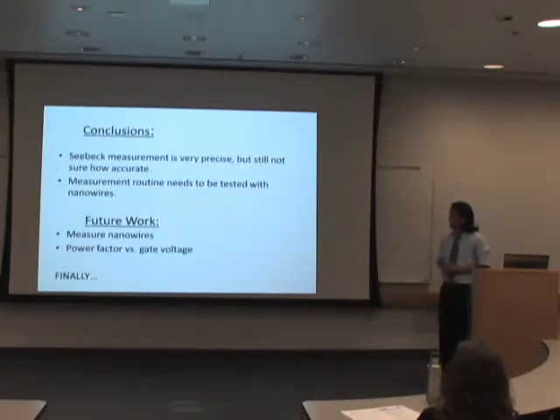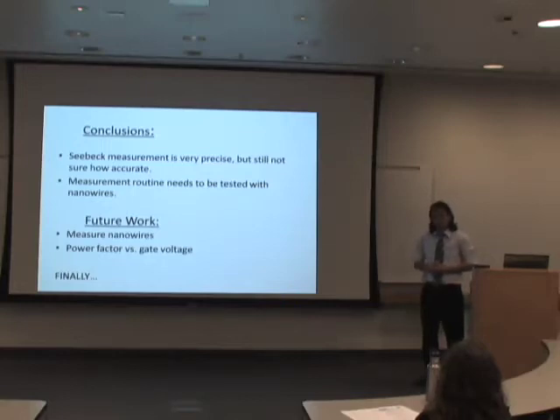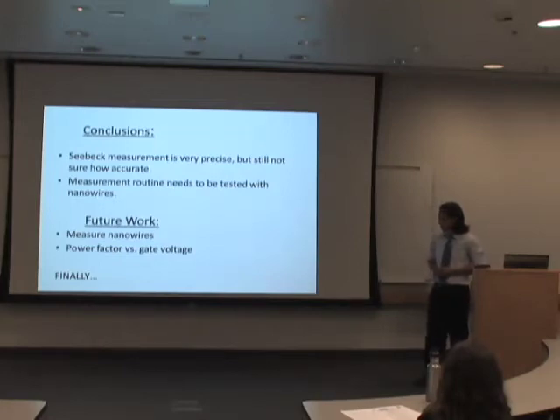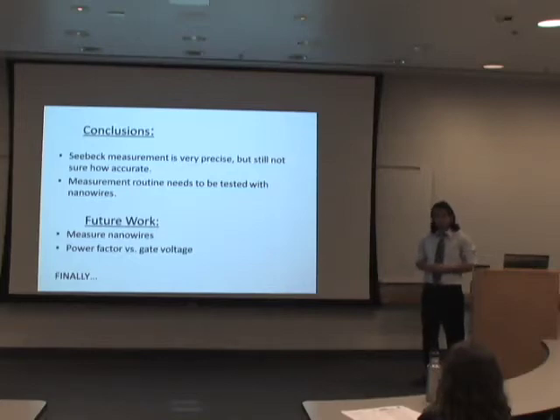So to conclude, the routine that we have put together and developed seems to be very precise. We get very repeatable results, but we're still analyzing how accurate it is, so we can find sources of error from the probes and the lines, which add Seebeck voltage also. We expect about 200 microvolts per K. We're getting 211, but it could also be 220 or 190. We don't know, so we need to analyze how accurate it is. We also need to test this routine with actual nanowires and not just the silicon sheet. So next year we're going to be working on measuring the nanowires and, after we get that done, analyzing how power factor changes with different gate voltages.